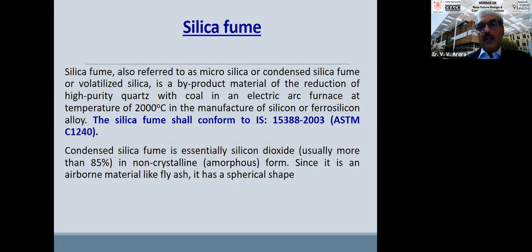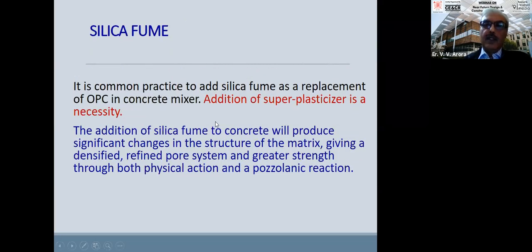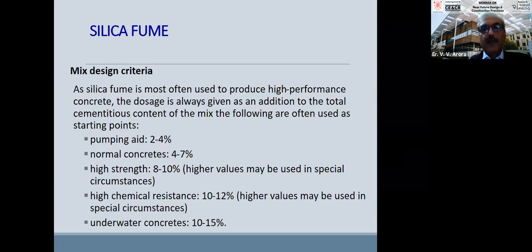The silica fume standard had come earlier, in 2003, long back. Addition of superplasticizer is generally a necessity when we use silica fume. The addition of silica fume will produce significant changes in the structure of the matrix, giving a densified, refined pore structure and greater strength, due to both physical action as well as pozzolanic action.